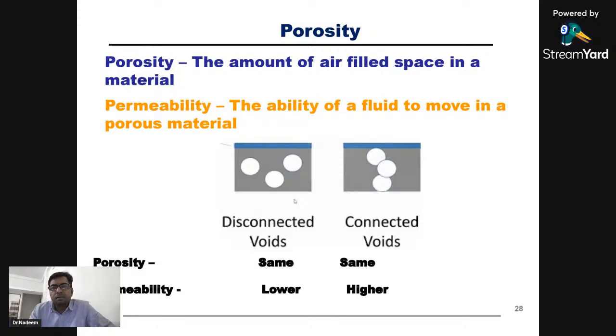So what are the things that are moving? A lot of chemicals, water, and we'll understand that later, which gain passage to enter into the concrete. So even if you have porosity in your concrete, if it is not connected, it is fine, not much harmful. But if it is connected and giving a way or passage, then it is quite harmful, which allows a lot of material to ingress. So if you see porosity wise, both are the same. But in terms of permeability, the left side is less permeable and the right side is highly permeable. So the left side of the material or structure has a low permeability, and the right side has a high permeability. This is just to understand the difference between porosity and permeability.